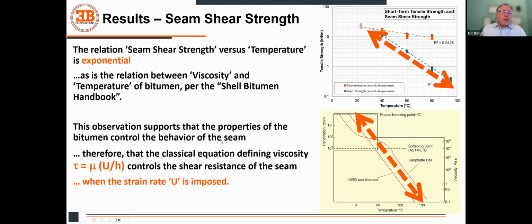But all these tests that we've done were under a fixed strain rate, which is what we do in a tensile tester. We apply a crosshead displacement, so it's like we have a fixed strain rate. And if we change the strain rate, we're going to have different values of force. But either way, that's what we have observed. We've modulated the temperature, which affects the viscosity, and we saw a relation for the seam strength which is consistent with this relation for viscosity.